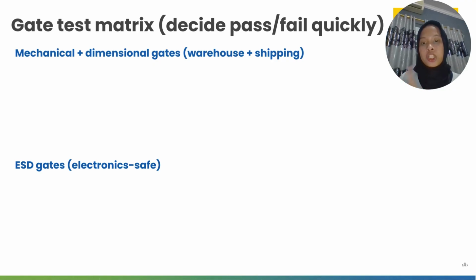Next is mechanical and dimensional gates in warehouse and shipping. The test is compression or cushion retention in the condition before and after hot humid aging, and the passing criteria is retain protective stiffness and no cell collapse. And the next one is warp measurement with stack load at 45 degrees Celsius, and the criteria is warp within tolerance, no brittle fracture on press test, and for film brittleness or tear after UV plus hot humid, it has to be no cracking at fold or bend and still integrity maintained.